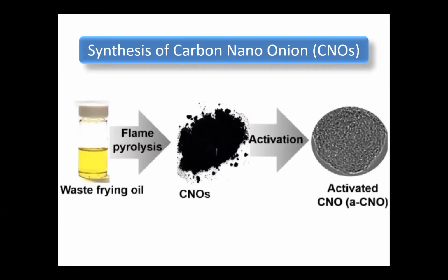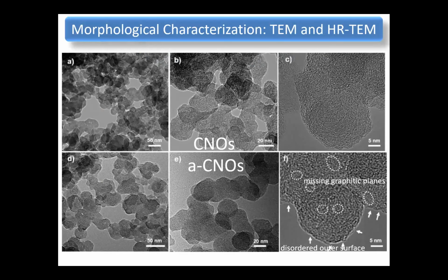Okay, sir. So for the synthesis of carbon nano onions, we have utilized waste frying oil, and we have synthesized carbon nano onions by the flame pyrolysis method. Further, these carbon nano onions have been activated by using KOH. We confirmed the morphology, carbon nano onions, by TEM and HRTEM. A, B, and C are the TEM images of carbon nano onions, where we can clearly see the agglomerated particles and concentric rings of stacked graphene sheets. In activated carbon nano onions, the agglomeration is less, and in the HRTEM image, we can see the disordered outer surface and missing planes in carbon nano onions.